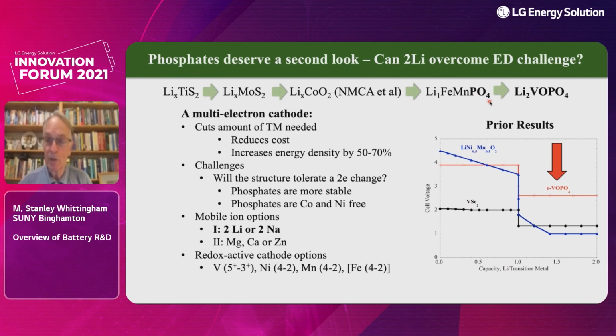But really, if we want to get the phosphates higher, we need to put 2 electrons in there. There have been a number of attempts to make multi-electron cathodes, and I'll show you 3 examples on the right-hand side here. The first one was work we did at Exxon a long time ago. Vanadium diselenide cycles 2 lithiums very readily at 2 volts and about 1.3 volts. Too low to be of any interest, but they showed the feasibility in this large lattice. Mike Thackeray showed the nickel manganese oxide with a bit of titanium in it would intercalate 2 lithiums, but again, you can see the second lithiums at a very low voltage, and so not of too much interest.